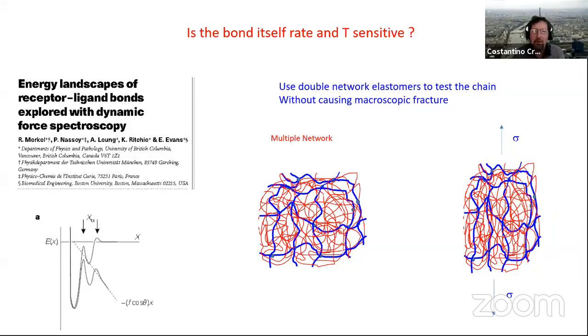Now, the next question that I certainly had was, how about the bond itself? The physicists tell us that it should be rate and temperature sensitive. It makes sense. If you look at this classic paper by Evan Evans and coworkers from 97, they show with very elegant single molecule experiments that if you apply a force to the bond, these are weak bonds, so they actually get good sensitivity, you can change the force. So the force should be defined as a function of the actual speed at which you're loading. And of course, the temperature is going to change the whole activation energy landscape. So there should be a difference.